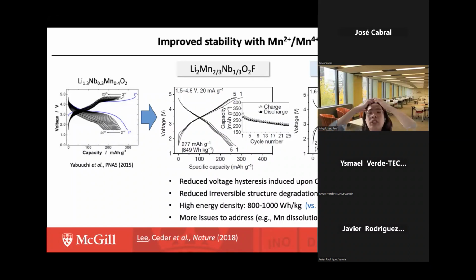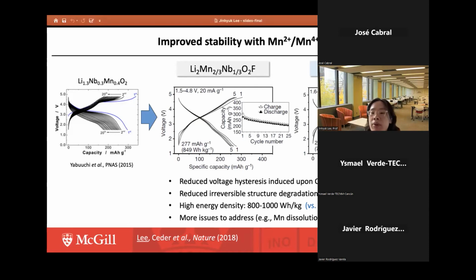We also found that these materials can deliver very high energy density, even up to 1,000 watt-hours per kilogram if you go up to very high voltage charging like 5 volts, which is not practical, by the way. This was much larger than what typical traditional cathode materials can store. But I would like to say there are other issues to address for these materials to become a practical cathode. For example, these materials are made of manganese, and manganese tends to dissolve in the electrolyte. So these additional problems have to be addressed. But this paper basically showed that you can engineer the redox process in these kinds of materials to achieve a novel cathode material.